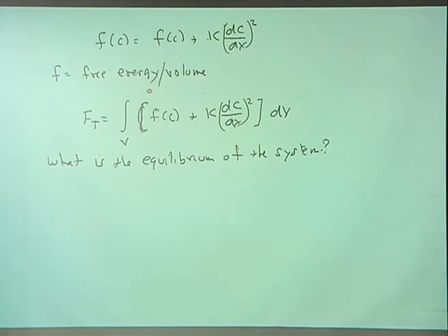And the question here is not what is the value of C that minimizes or extremizes this free energy. We're going to ask what is the function of C that minimizes this free energy. So we're going to ask something very much more general. It says, what is the equilibrium in the system? In other words, what is the value that extremizes